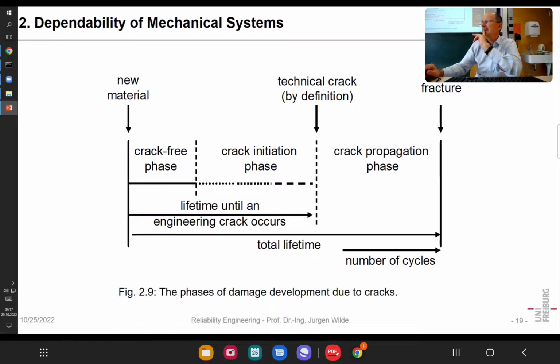You can see that, for instance, when you have a polished part of steel, which is really polished, and then after a certain time, you see some kind of weak pattern on the surface. Yeah. And when this pattern becomes stronger, you get a crack, which is more a crack by definition. You cannot say here that's a point where it's just that surface pattern, and here that crack. It's more a sliding transition. But in the end, engineers take something like an engineering crack, which means the part already had become a little weaker. Yeah, a few percent weaker, and that is a crack by definition.